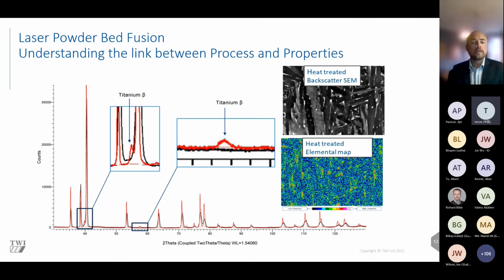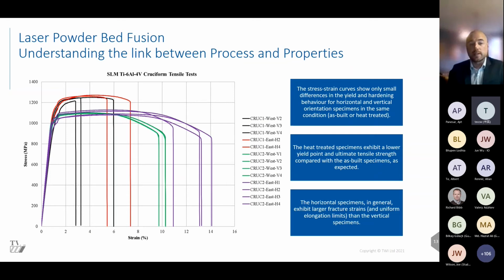So when we look at this X-ray diffraction pattern, we see almost no beta phase present in the black curve, which is the as-built condition. It's cooled so rapidly, it's all been consumed into a martensitic phase. And so we should expect there's going to be almost no ductility. And when we do the tests, we see that exactly.